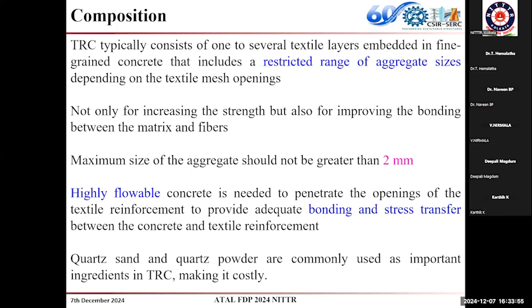So like that, for each and every type, we have to keep in mind that when we are going for a new type of concrete, we should change the proportion accordingly. So here in this case, there is no coarse aggregate, and the maximum size of the aggregate should not be greater than 2 mm, because we have to maintain the integrity between the fiber which is placed, the textile fiber which is placed along with the matrix.